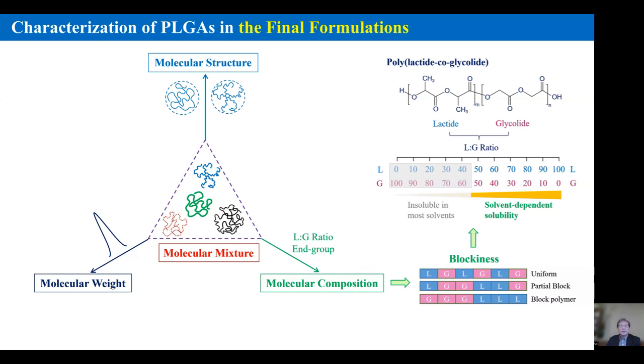So whenever we characterize PLGA, we usually talk about molecular weight, and then molecular composition, LG ratio, as we just heard about, and end group, whether ester or acid end group. And then we had to understand the molecular structure because one of the commercial products contains a nonlinear, star-shaped PLGA. The question becomes when a formulation contains more than one type of PLGA, it may have different molecular weights, different LG ratios, different end groups, and different molecular structures. Then the question becomes, how do we characterize this complex formulation? And that's the question FDA had a long time ago, and we have been solving the problems one by one.